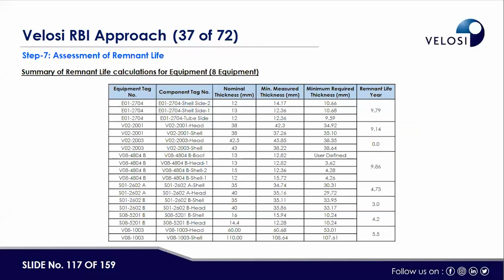Here is the summary of remnant life calculation for equipment. For 8 equipment, we have the results shown here. For example, remnant life in years is 9.79, 9.14, then 0, 9.86, 4.73. This is done with nominal thickness, minimum measured thickness, and minimum required thickness, and then remnant life is calculated as per the formula. All details are not shown here.